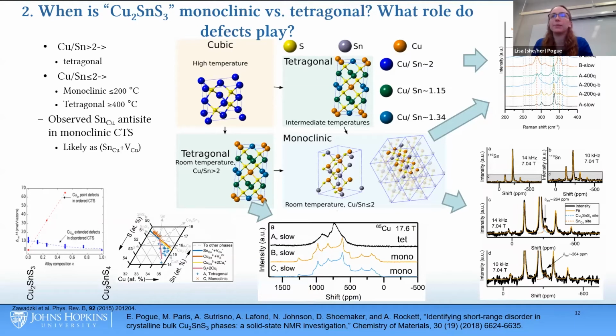The second question I was addressing was about copper tin sulfide, another phase in this broader system being used in solar cells. Some groups get the monoclinic phase, other ones get the tetragonal phase, and it was unclear under which processing conditions the different phases would form. And so I found the conditions under which these would form and found evidence of an instability in copper-rich conditions that caused the disordered tetragonal phase to be more stable.